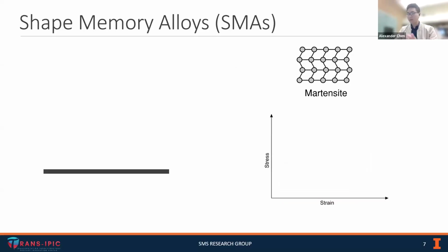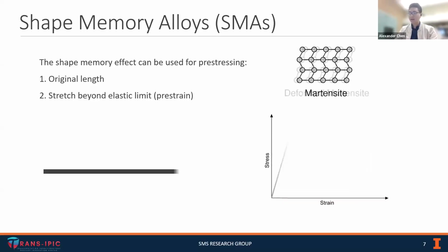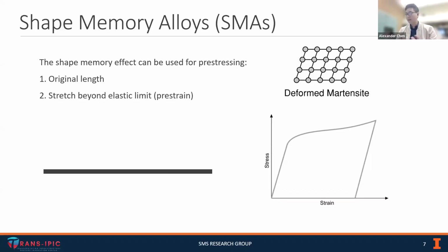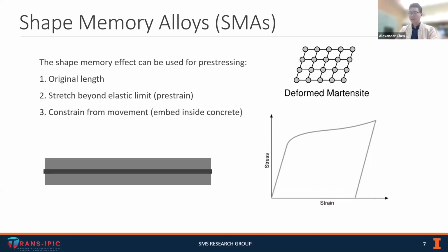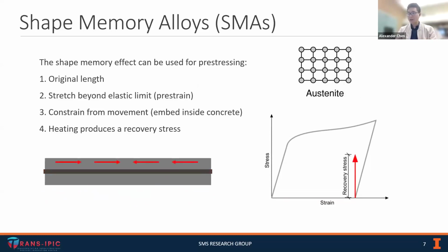Now if we want to use this principle for pre-stressing concrete, we start with the same steps. We take a bar of SMA and pre-strain it. At this stage, we add the additional step of placing it inside of concrete, which constrains it from movement. Applying heat at this stage causes the phase transformation, and the SMA imparts a recovery stress onto the concrete. And this recovery stress is what pre-stresses the concrete.